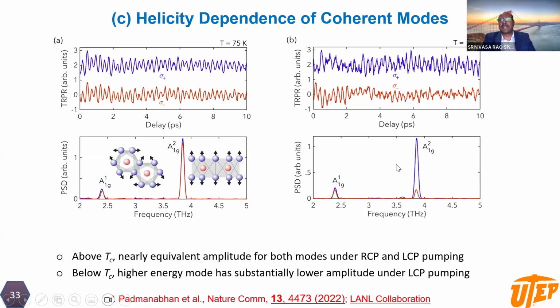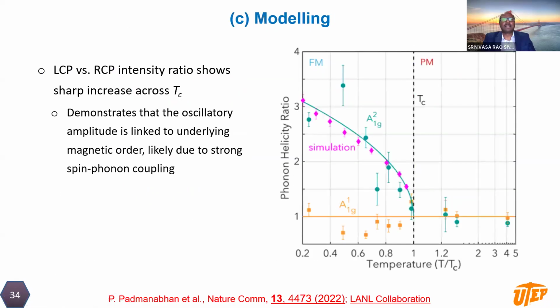So what we did next, we tracked the intensity ratio of the A2G mode between sigma plus and sigma minus as a function of temperature, and that is plotted here. This is the phonon helicity ratio for A2G as a function of temperature, and this is the A1G phonon helicity ratio. You see that the intensity of the A1G phonon mode is practically independent of temperature. Our theory collaborators simulated this pattern by incorporating the magnetostriction effect on this compound upon photoexcitation. So this trend mimics the temperature-dependent magnetization of this compound, and it follows the temperature-dependent helicity ratio. So both go hand in hand.